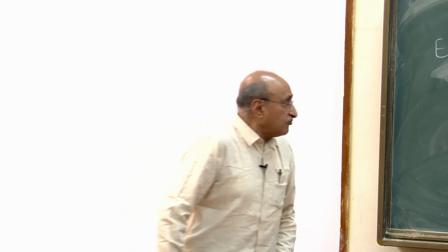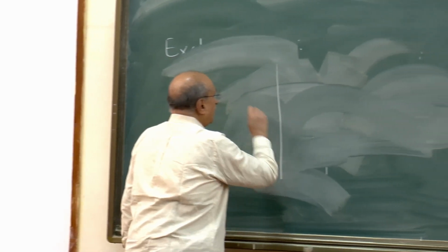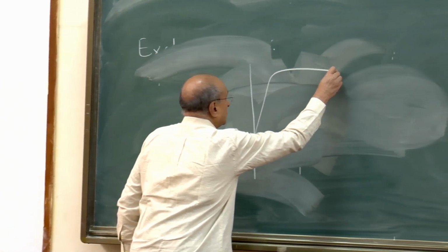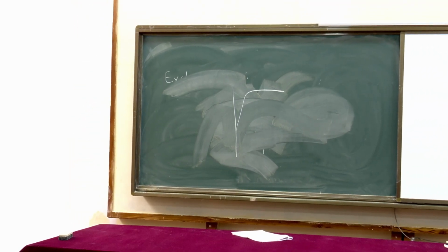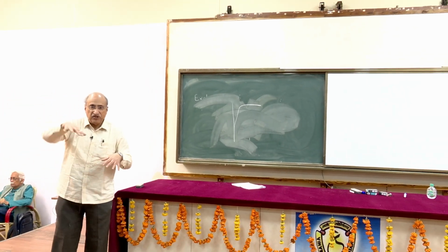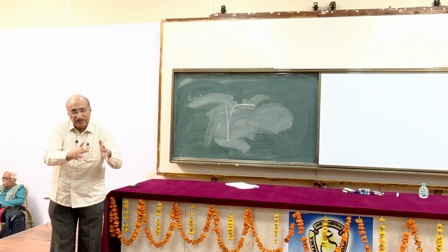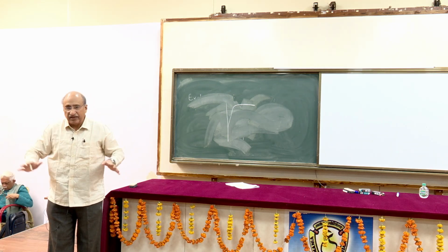All right. In that case, what happens if you start with a demagnetized state and you want to magnetize a sample along one of the easy directions, let's suppose the C axis, which is the easy direction? You have magnetized it and it has reached saturation. It means now the entire material is a single domain material. Either the favorable domains have increased their size, or other domains which were in a different direction have rotated themselves and aligned and merged with the same domain. Eventually, in saturation, you have only a single domain.